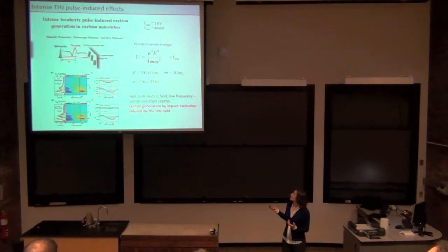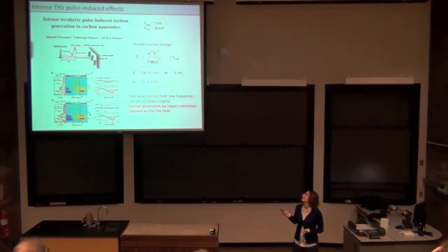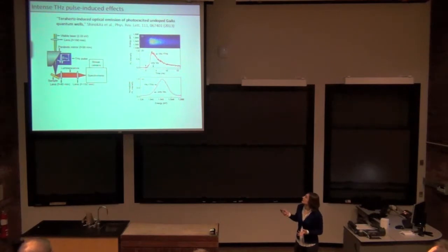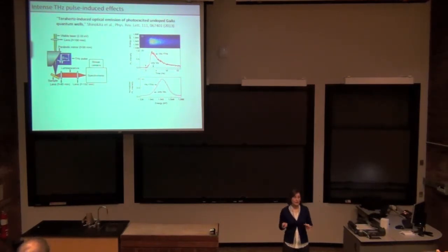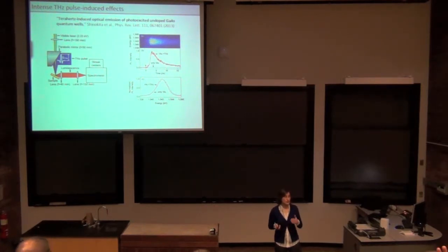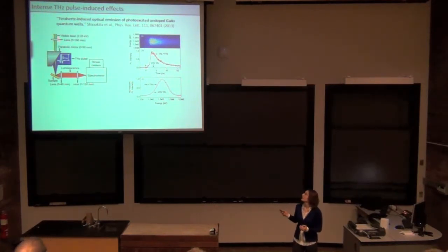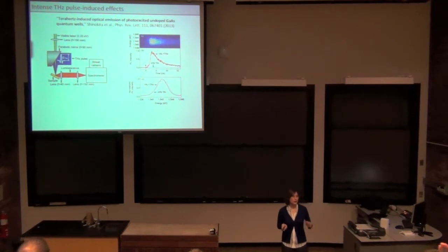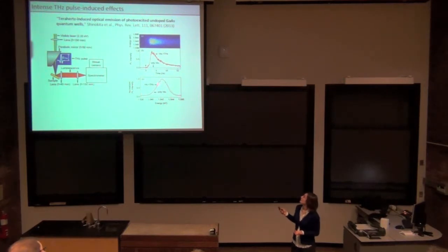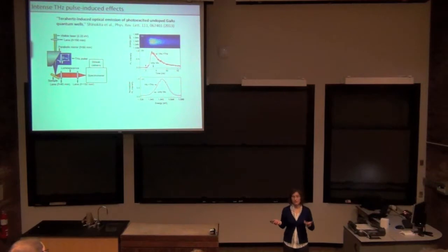So, exciton generation by impact ionization induced by terahertz pulses. In the final example that I want to show you, this was done on gallium arsenide AlGaAs quantum wells. They looked at room temperature. They can excite photoluminescence using a quasi-CW laser. Of course, you see the photoluminescence peak, all centered around 1.42 eV.